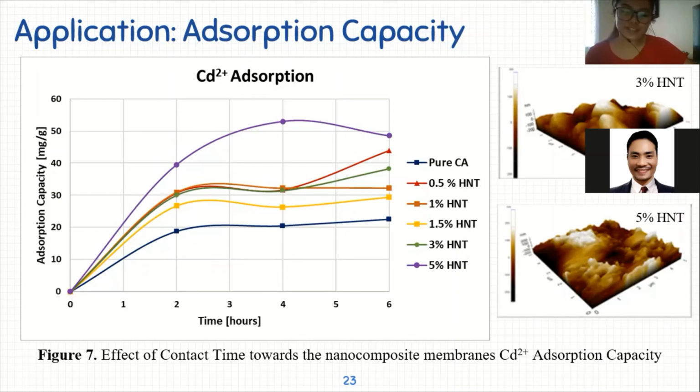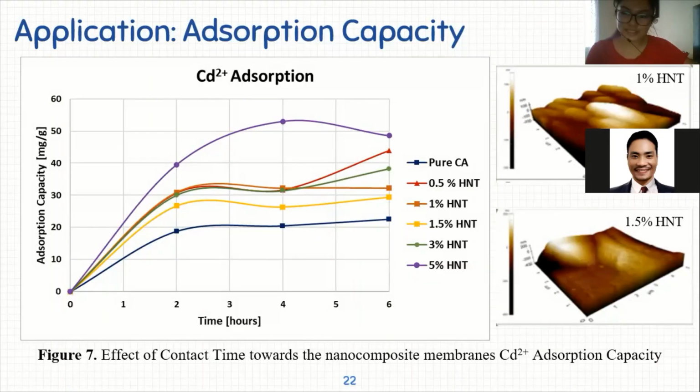So it's better if there's a high number of peaks and valleys inside a bigger valley, because if it's inside a bigger valley, it is not as affected by Brownian motion or other motions, say stirring the aqueous solution. If it's just peaks and valleys on an even surface, as you can see previously in sample 1%, it's very prone to being affected by Brownian motion, the rapid, random and erratic behavior of water molecules.